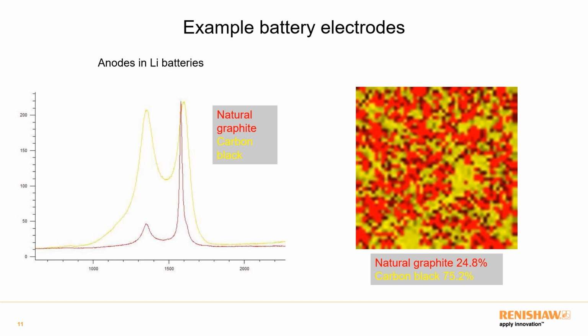So we see natural graphite in red and carbon black in yellow. And these have very distinctive spectra. And we can plot this over a map of the same area as in the previous slide. And you can see we've got a mixture of carbon black and natural graphite, pretty much spread evenly about the surface. Carbon black accounts for 75% of the material, and natural graphite is about 25% of the material.